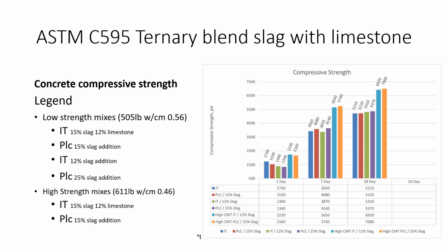When we've done that testing, and this is our own in-house testing, we can see that the results are showing similar results. The first four that you're seeing here are done at a 505 pound mix at a 0.56 water cement ratio, non-air-entrained mixes. These were done in the lab. And then we did a high strength one to see, is there an aspect difference? We're doing it with lower strength concrete versus higher strength concrete, and we can see we're getting similar results.